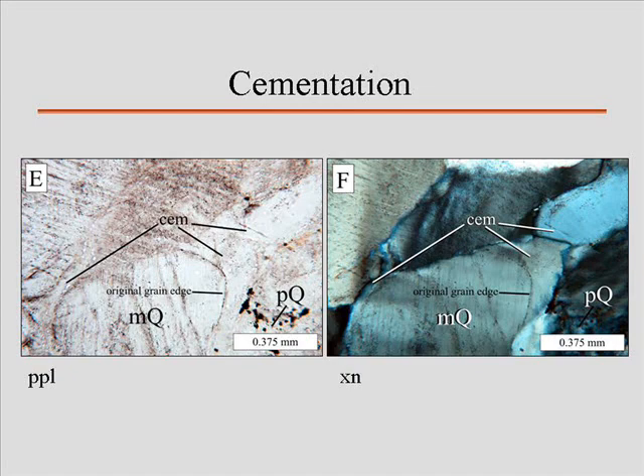When you go back and look at those cement thin sections for the lab that you're doing this week, look to see if you can see the euhedral faces. Moreover, and this is really cool, the nice thing about quartz overgrowth cements, because they're chemical precipitates on top of a quartz grain, is they tend to carry on the optical characteristics of the grain. Case in point, if that's the optic axis of a quartz grain here, that's the optic axis of a quartz grain there. When the cements start to form over top of those grains, the cement that forms is in optical continuity with the grain that it is precipitating on.